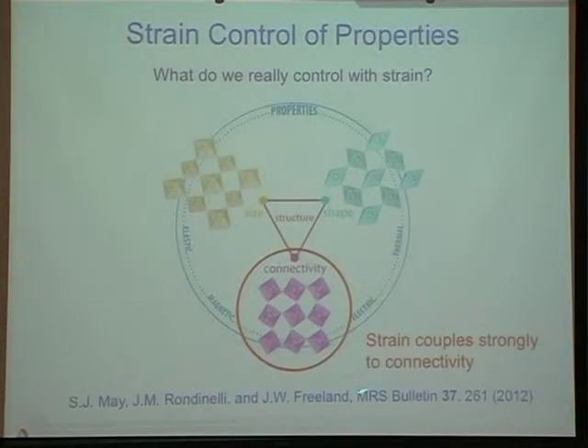So what we've learned in these materials is that if you think of the octahedra as your functional unit, there are basically three things you want to control in a strongly correlated material. You want to control the size, which typically correlates with the charge. You want to control the shape. This has to do with which specific orbitals are occupied. And you want to control the connectivity. That is how the bond angles are bending, but also the symmetry of how the bond angles are bending. And I'll say more about this in a minute.